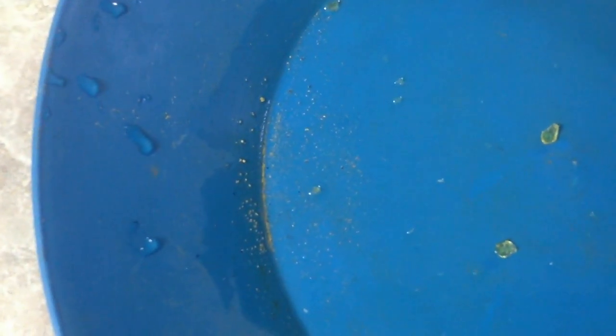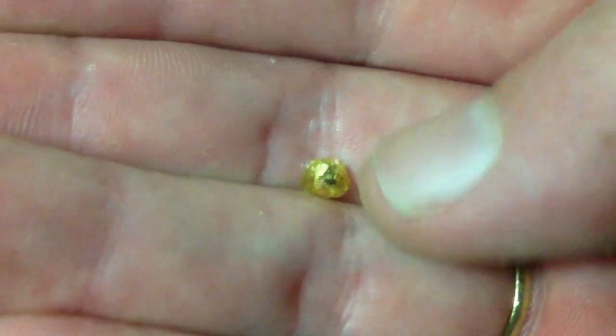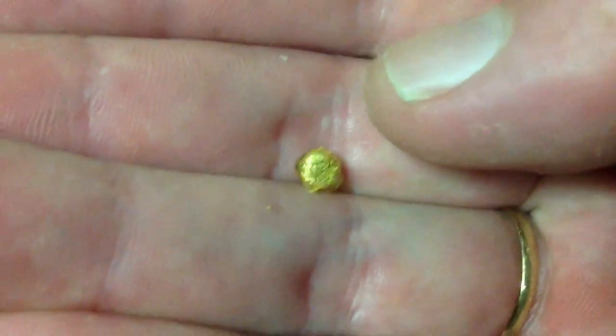And that was the gold in mercury. So that's what's left of the borax slag. As you can see, I didn't quite get all the powder out before when I did the melt, so there's still a bit of powder there. That's the gold we managed to clean up — still a little bit of slag on it probably. Unfortunately my calculations were extremely off. This only ended up being about 0.7 to 0.8 grams.